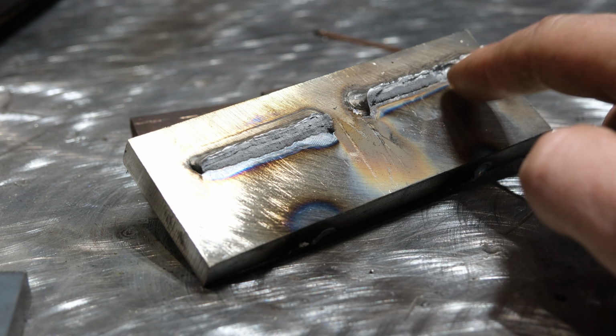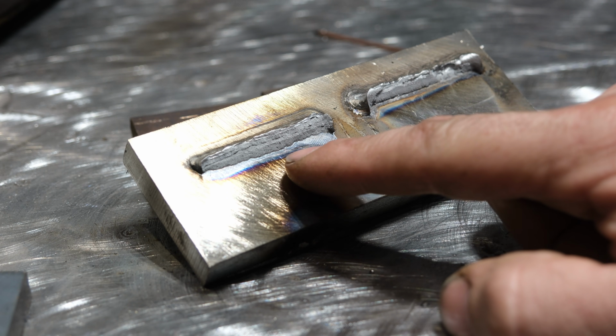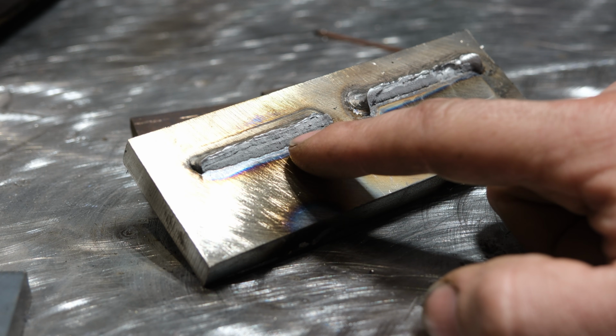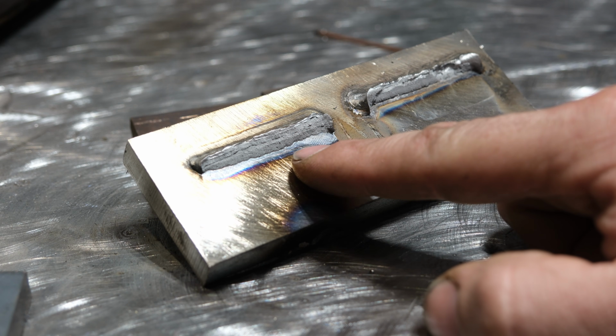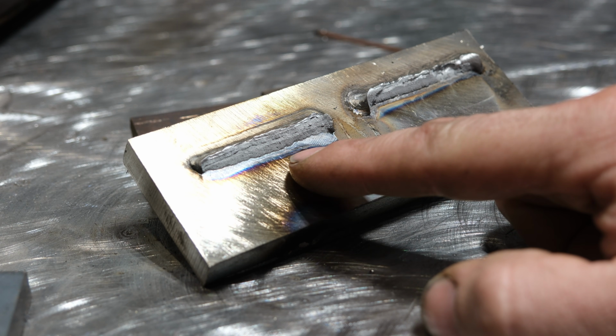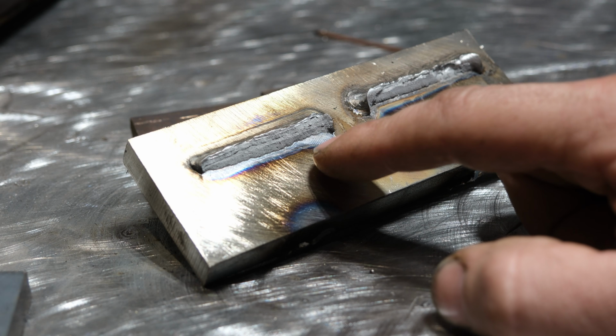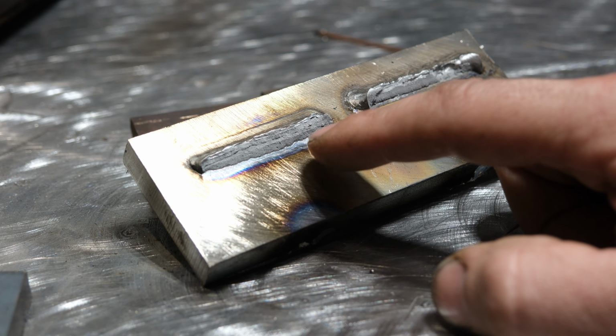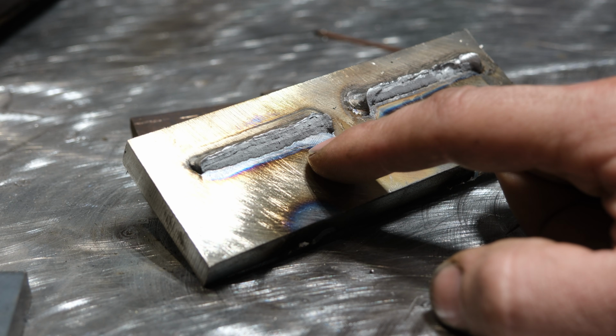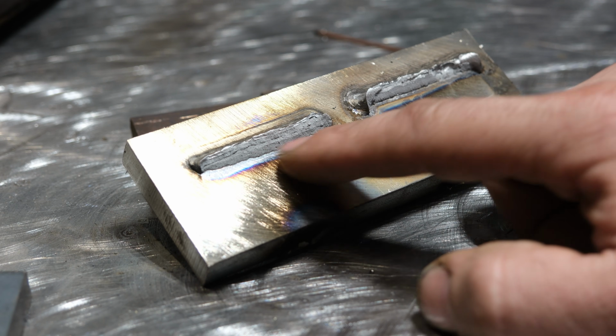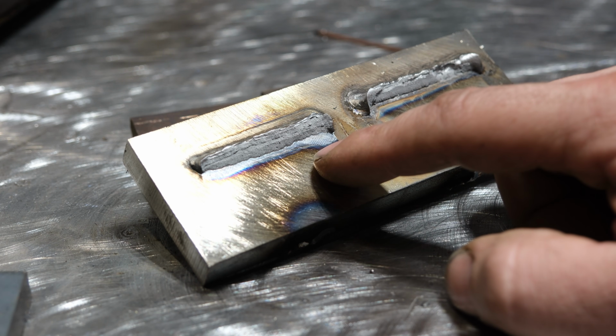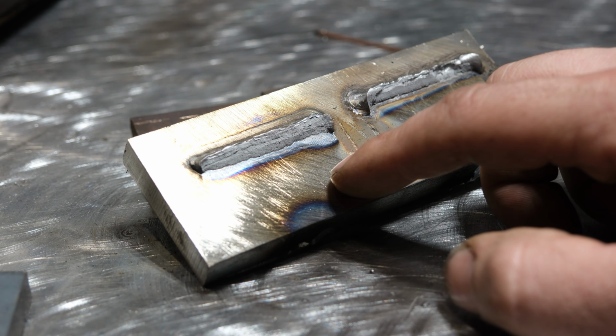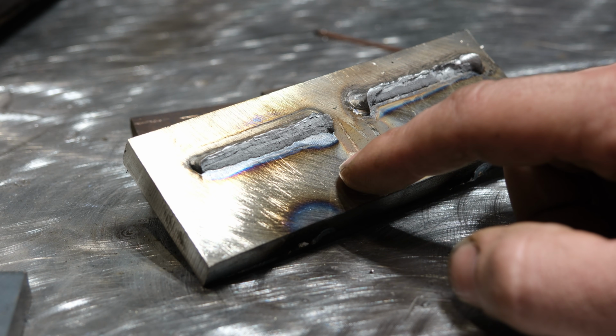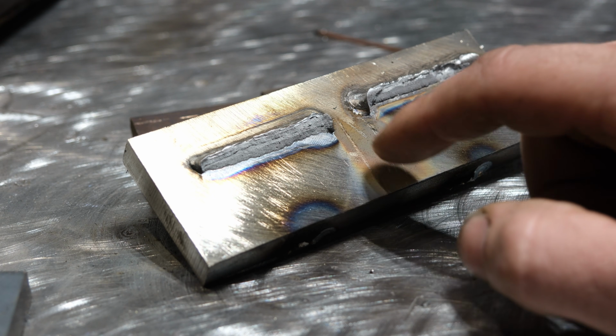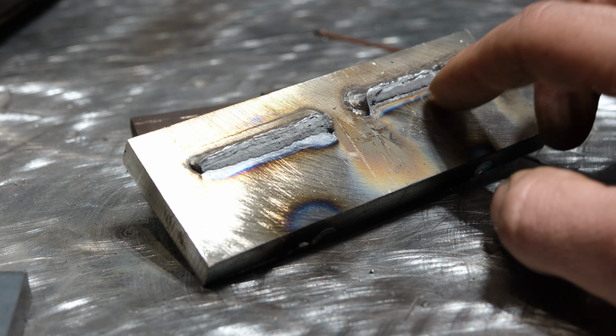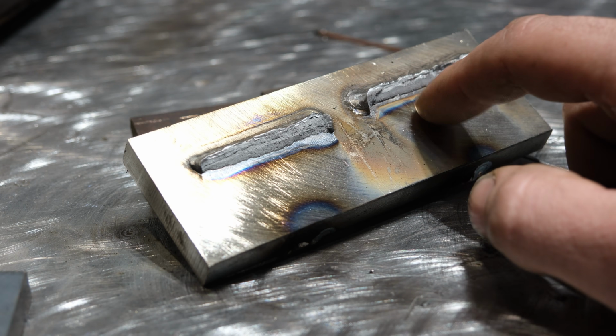So interestingly enough, you can see the heat affected zone colors are actually a lot wider with the TIG weld over the stick weld. And again, it comes down to, even though we deposited less metal per pass, we had to do more passes, thus put more heat into it with this over the stick. And depending on what type of material you're welding, that extra heat input may be of a concern because it could weaken the material in the heat affected zone due to the change in temperature and basically the annealing or the heat treatment that essentially comes out of this. So it's all things to be aware of, especially with critical, high strength alloys and stuff.